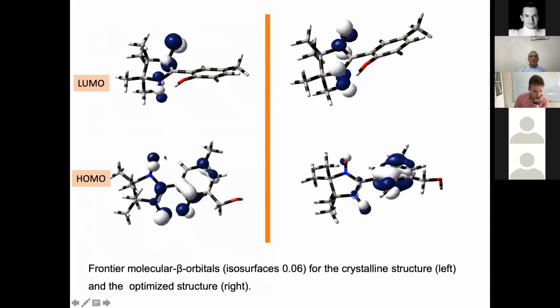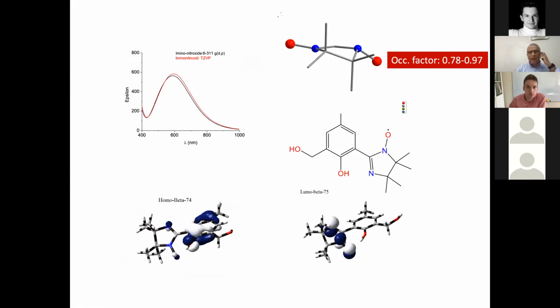So these are transitions between the HOMO and LUMO orbitals in the molecule in the crystal, while this one is the so-called optimized, I mean the one with the two nitronyl nitroxide groups coplanar, and for sure this is the species we have in solution. And because we have this occupation factor and the remaining molecules are iminonitroxide, we simulated the spectrum and we found this band that is still present in the crystal phase.